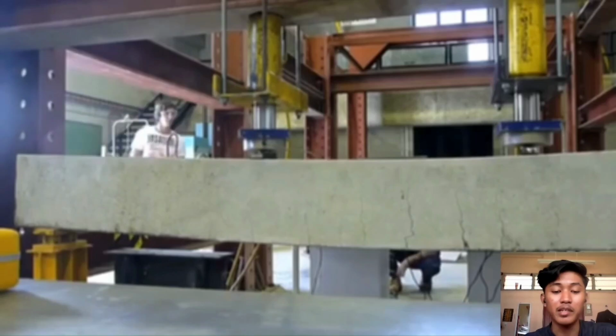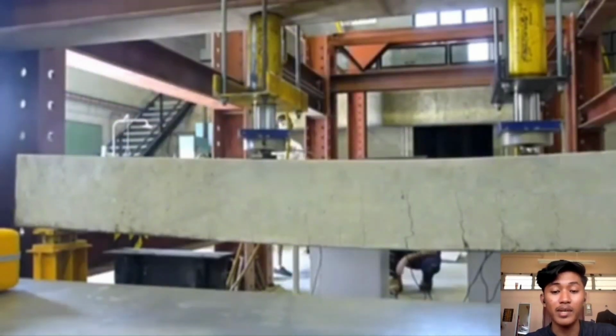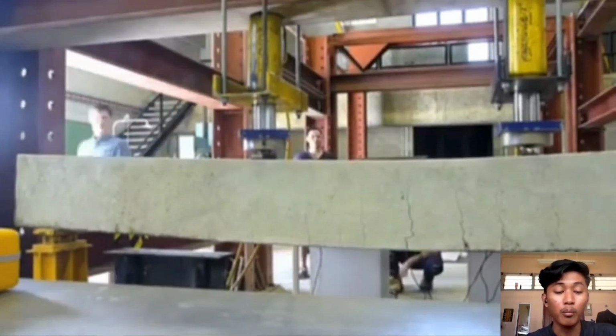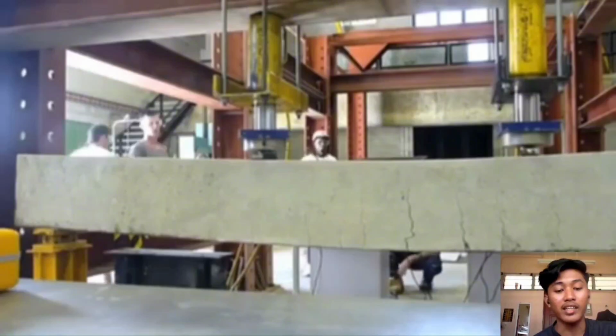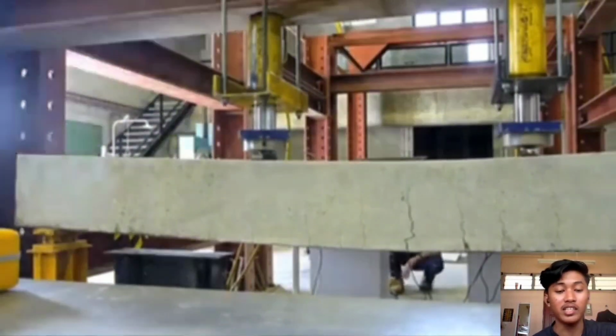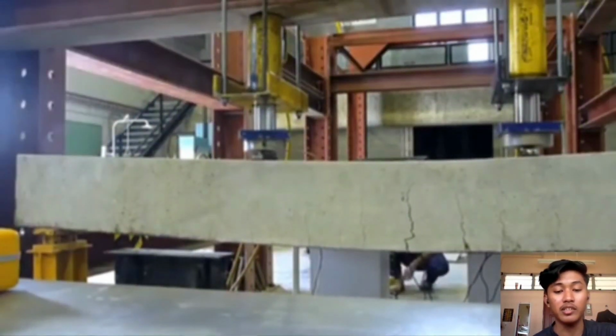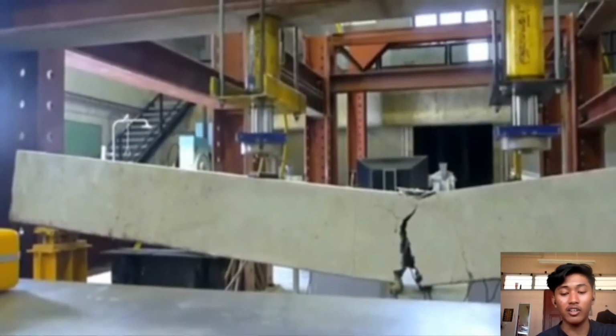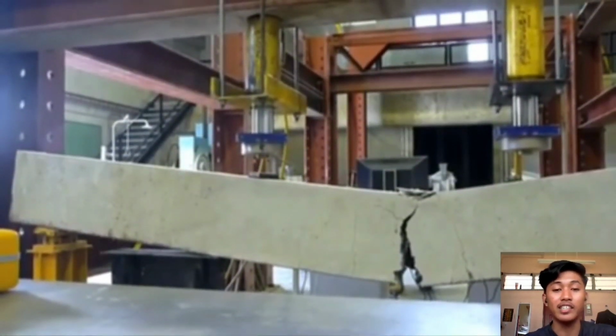Every SCC beam specimen has been tested for failure under a bending test, which is the 4-point flexural test, at various ratios of A/D, which means the shear span to effective depth. The load applied was increased continuously until failure at a displacement of 0.01 mm per second.